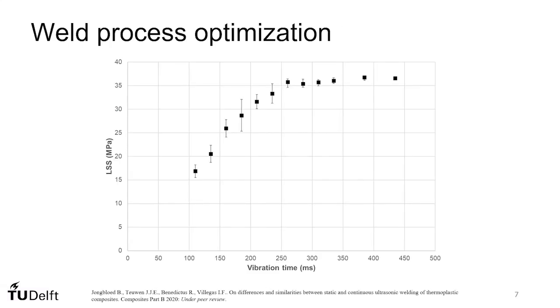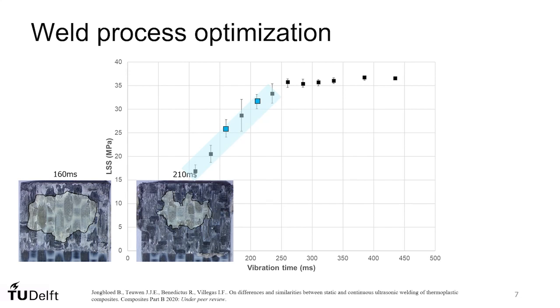Finally, let's look at the role of single lap shear testing in the optimization of a welding process by investigating how changes in different process parameters affect the quality of the welded joints. In this particular graph, we see the single lap shear strength of ultrasonically welded joints obtained at different vibration times. Let's first focus on the first region of the graph, where the single lap shear strength increased with increased vibration time. If we look at the fracture surfaces of the joints welded in this region, we see that the welding process started at the edges of the overlap and progressed towards the center. Hence, as the vibration time increased, so did the amount of welded area and the single lap shear strength.